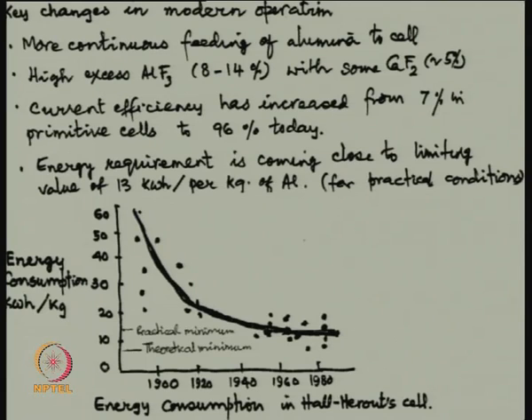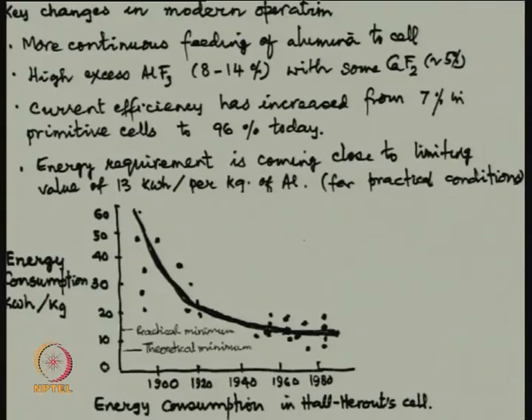96% is going into decomposition of alumina to aluminum. Energy requirement is gradually coming to a limiting value of 13 kilowatt hour per kg, almost the practical minimum. These two dots are wrong, this should not be there. The theoretical minimum is even less, it is about 6. Why theoretical minimum? Only the power required to dissociate aluminum, but we need some energy also to keep the electrolyte hot. So, the practical minimum is above theoretical minimum, but in the last 20 years or so, industries are almost able to bring it to the practical minimum. I will give you some figures to this effect a little later.